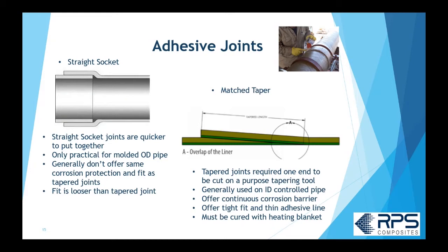You'll notice from the green line, one of the advantages of the tapered adhesive joint is it gives you a pretty much continuous corrosion barrier. There's only going to be a tiny layer of adhesive exposed at the edge of the taper. And it also gives you a very tight, very thin adhesive line. And because you have that thin adhesive line, you need to cure it with a heating blanket.